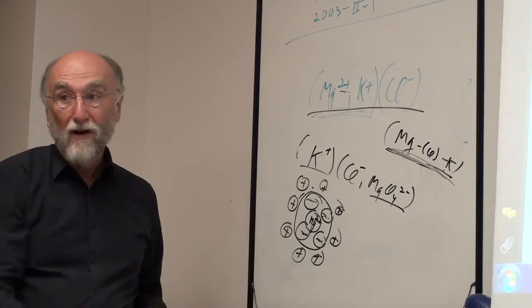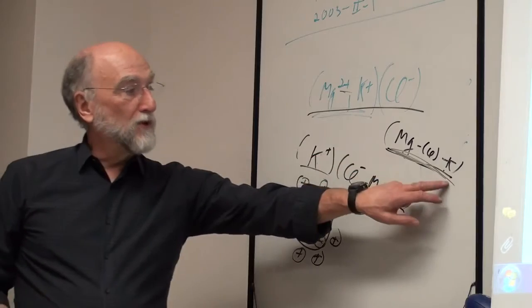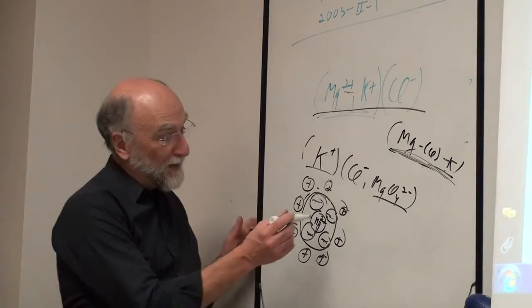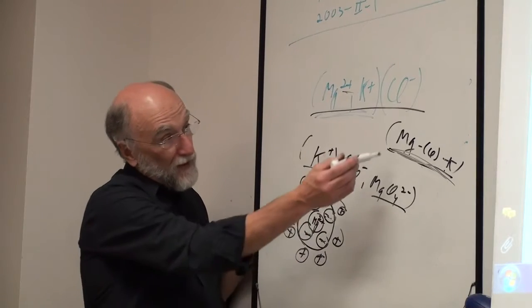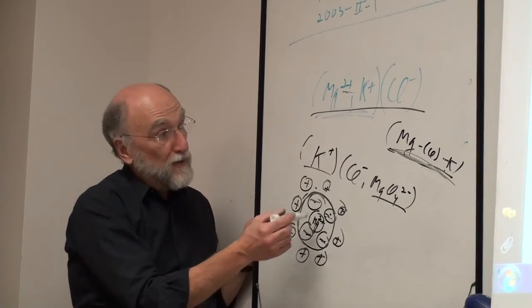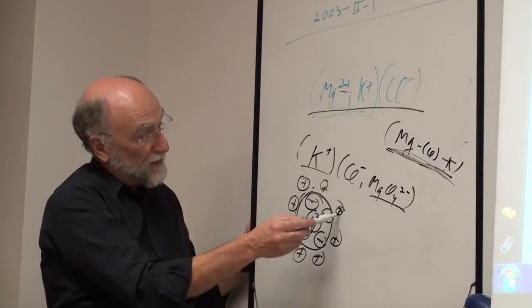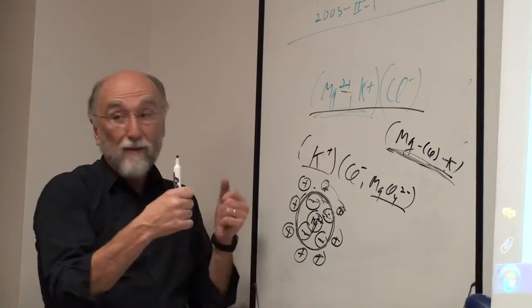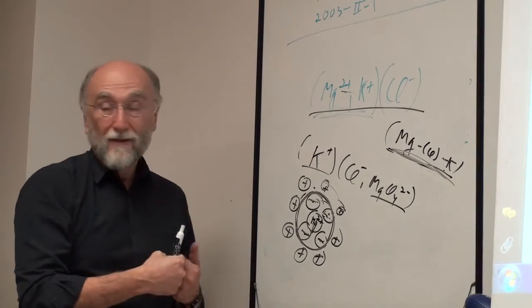So therefore we have complex anions, and therefore the quasi-chemical model doesn't agree with reality. But I say yes it does, because in the quasi-chemical model you have magnesium with 4 chlorines, and because of your ratio of 2 to 1 of the Zs, potassium is in the next shell, so clearly this unit is going to vibrate like an MgCl4 unit.